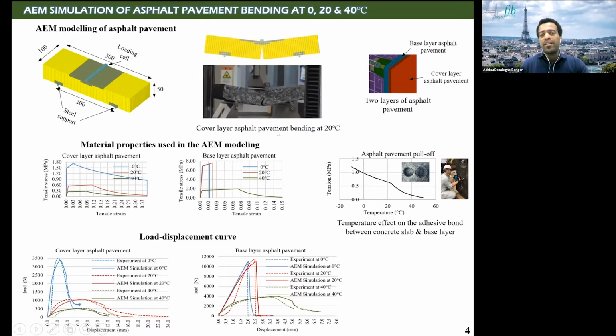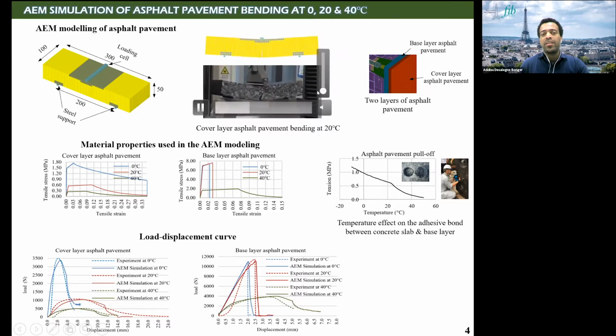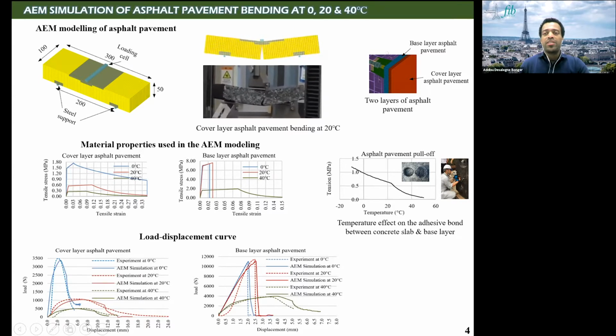This one is the cover layer at 20 degrees centigrade. Crack originated at midspan in the bottom surface, then propagated upward until full collapse. As I mentioned, we provide two asphalt pavement layers, base layer and cover layer. So we carried out asphalt pavement bending for both asphalt layers. This is in the numerical simulation.